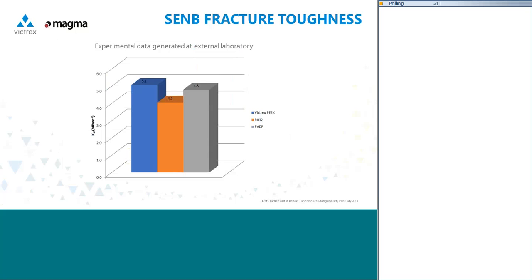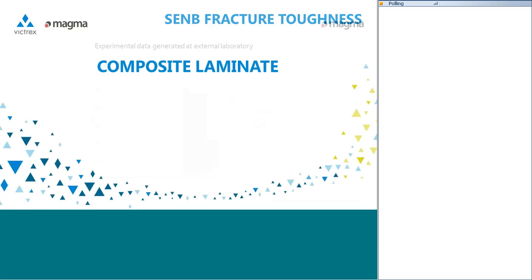And you'll see here we've compared VICTREX PEEK polymer, nylon 12 and the PVDF polymer, and you'll see that actually there's not a huge amount between them, but in fact the PEEK polymer is the toughest of the three. So PEEK is clearly very well suited as a pipe precursor. It has a very high resistance to crack propagation.